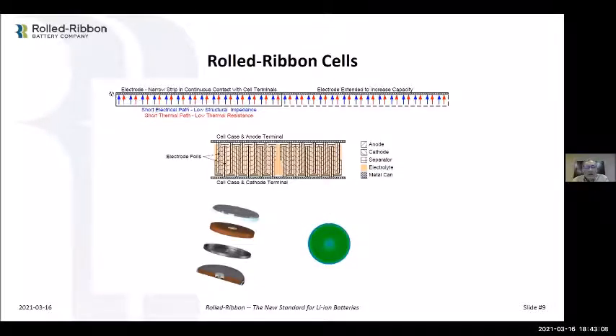What you see in the structure then is our electrode is this narrow ribbon that's rolled up, hence the term roll ribbon of electrode. And in our model, what happens is all the current doesn't have to run this long stretch of the electrode ribbon that we've created. It goes from where it generates on the ribbon to the nearest edge, comes in contact with the pan, and leaves. So we have a very short path for thermal and electrical, and that reduces the impedance of the cell. So we have less I squared R losses. It decreases the thermal resistance because now we have metal, all the heat's generated on the working surface, the sheet, the electrode, and it connects directly to the pan, which is the outside world, and then we go away.